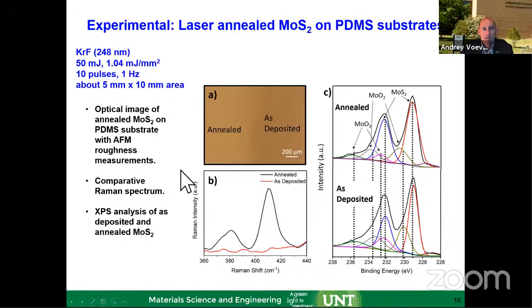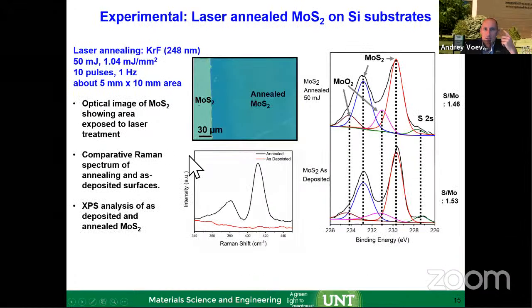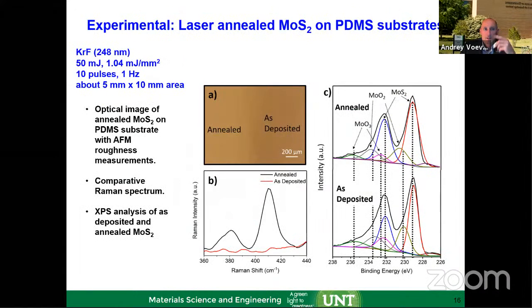So some experiments are shown here, comparing as deposited and annealed on a PDMS substrate. The previous chart was on silicon, and here this is on a stretchable polymer substrate. As deposited is amorphous, and after annealing you can barely see the difference in optical, but if you look at the Raman, you'll see that the crystalline material definitely shows up.